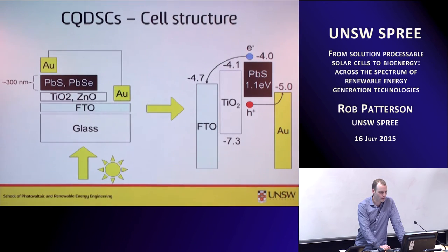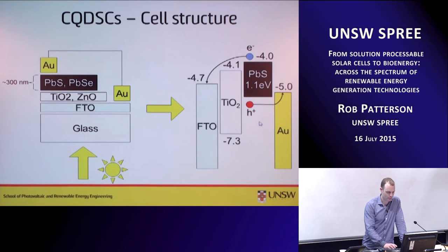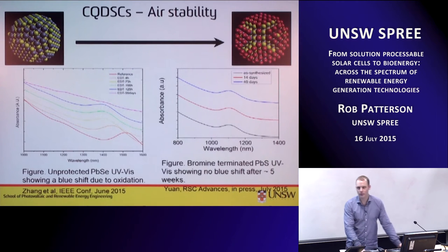Here's the cell structure that we typically use. It's a typical cell structure also employed for organic solar cells and things like this. So, glass, TiO2, FTO, and then we have our lead sulfide and lead selenide quantum confined material on top. And here are some of the band offsets, which show you basically which materials are N-type and which materials are P-type.